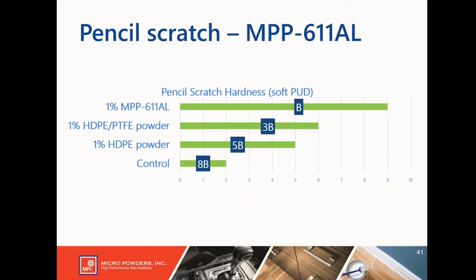But then if you take the 5B example, the 1% high-density polyethylene powder, but you put the aluminum oxide inside the wax particle, you get that top bar, 1% MPP-611AL, and you improve from a 3B with the PTFE-based material to a B. You improve from a 5B with just the polyethylene powder to a B with the polyethylene alumina composite powder.